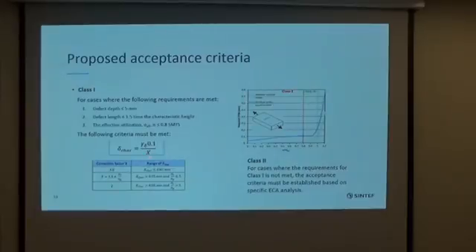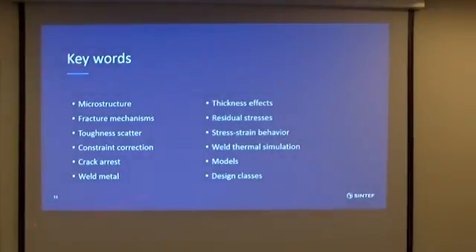Of course, we also introduce constraint parameters. As we mentioned, we tested, for instance, SENT and SENB specimens with different crack sizes, and correlated the different geometries with toughness. If it's class 2, in this area, it's critical, and we recommend that an ECA, engineering critical assessment, should be performed. These are the most important issues we think are important to cover. I conclude my talk with some keywords: microstructure, fracture mechanisms, toughness scatter, constraint correction, crack arrest, weld metal, thickness effect, residual stresses, stress-strain behavior, weld thermal simulation to simulate microstructures, and models. Numerical models, simplified, empirical or analytical models are important for refining our design classes.